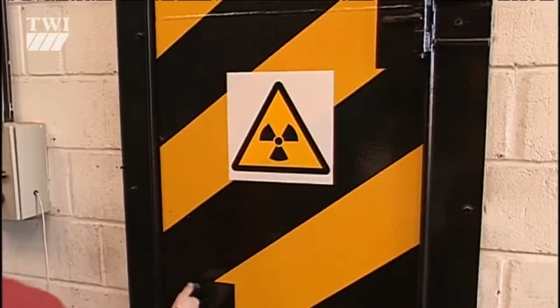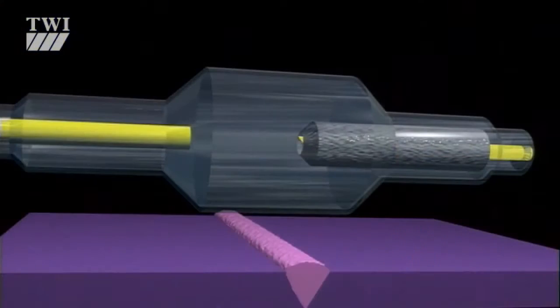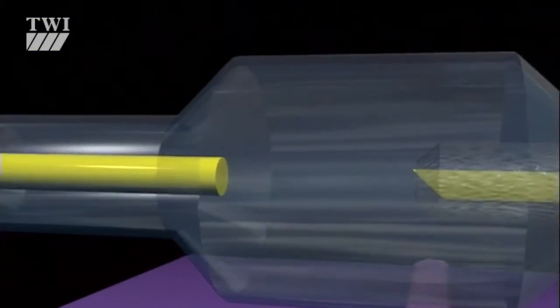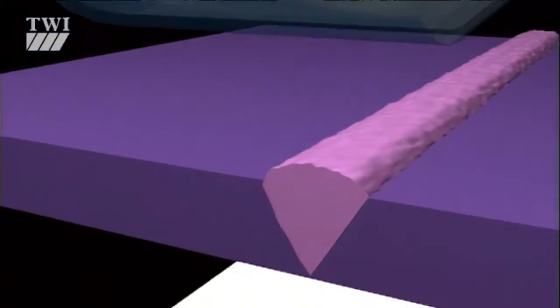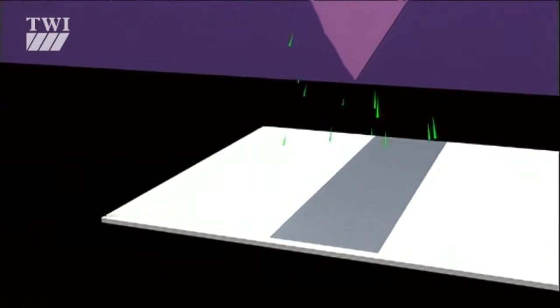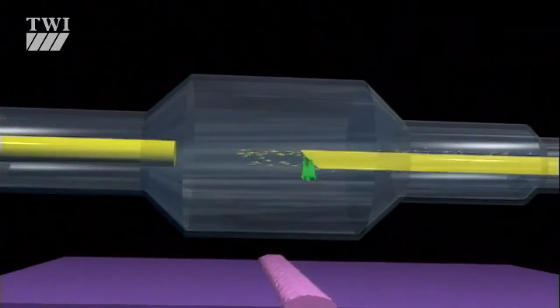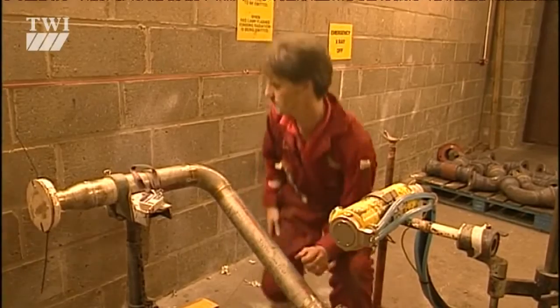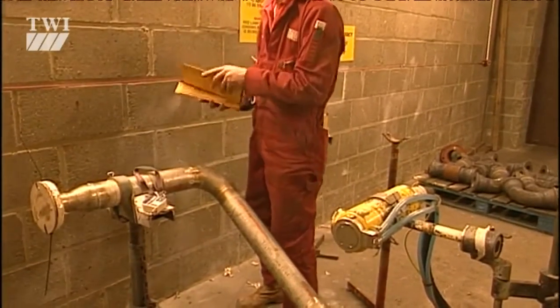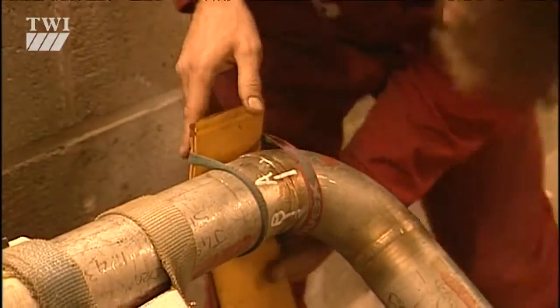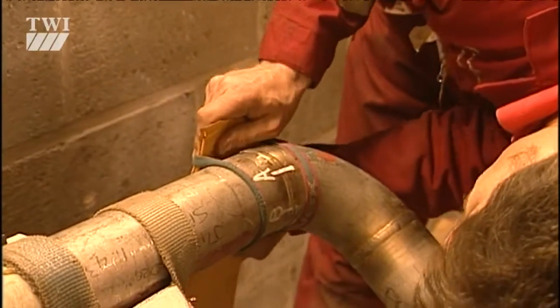Radiography is an entirely different type of non-destructive testing. X-rays are produced by directing a stream of high-velocity electrons across an evacuated chamber against an angled target material. The x-rays pass through almost every material and can be detected by a sensitive film on the other side. However, a high-density material will absorb x-rays, while low-density materials allow a greater proportion of them to pass through. For radiographic inspection, there's no need for surface preparation before testing.